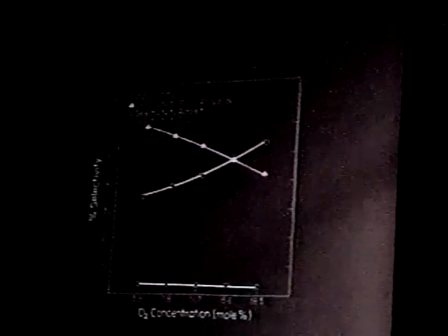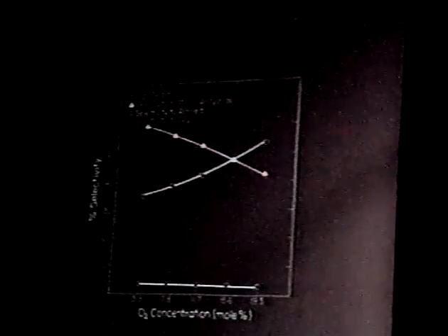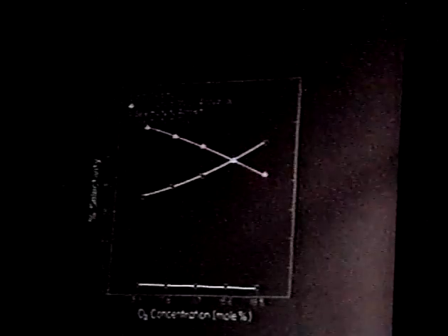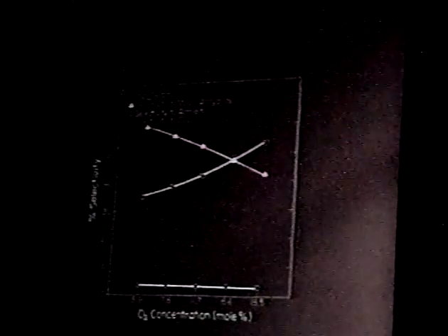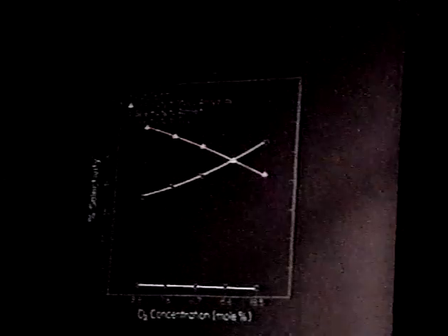Finally, when we come to furan oxidation, again concentrating on the molybdenum trioxide catalyst, we see that the selectivity to maleic anhydride decreases much more pronouncedly, and the selectivity to carbon dioxide increases almost as rapidly as maleic anhydride selectivity decreases. And we see very small quantities of acrolein being formed, and there are almost no other reaction products.